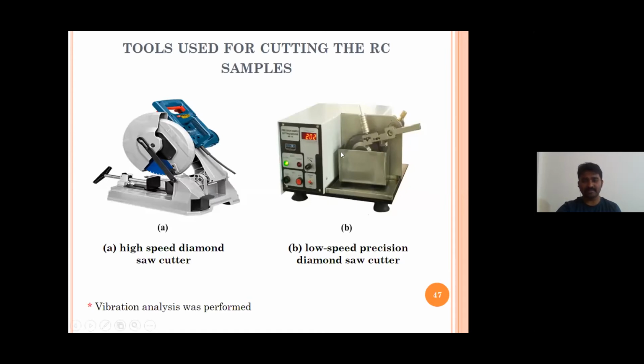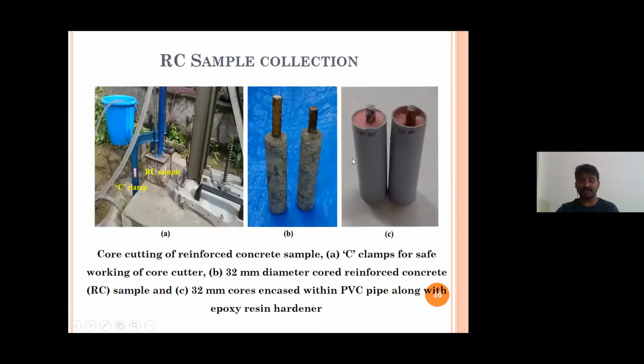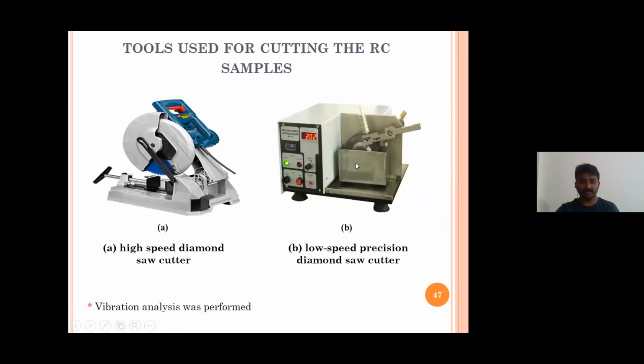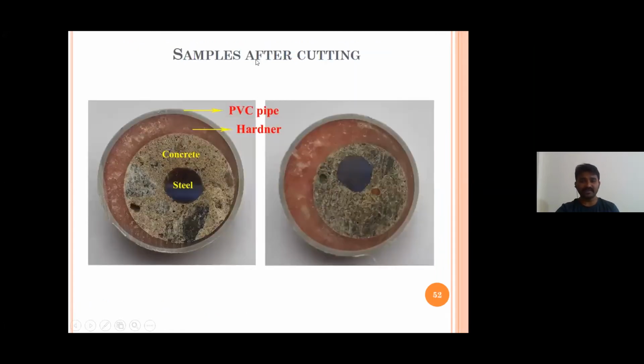This is the precision diamond saw cutter supplied by Ducom. See, this is the blade, and here we put our sample. Okay, to cut these samples in high speed cutter, hardly it takes 8 to 10 seconds. But in low speed precision diamond saw cutters, it takes around 4 to 5 hours to cut this cross section like this. Okay, so once you cut, this is the way you see the samples after we cut.